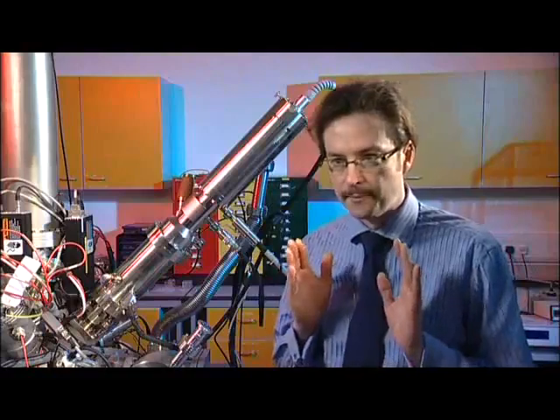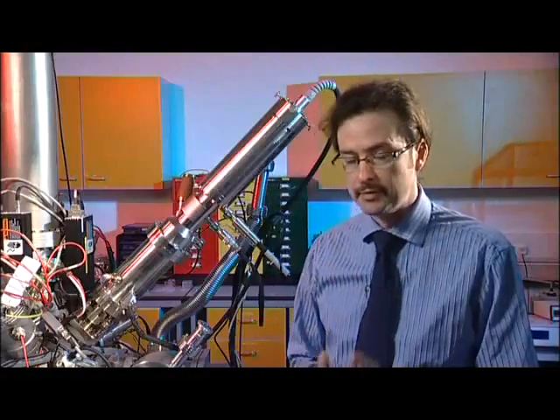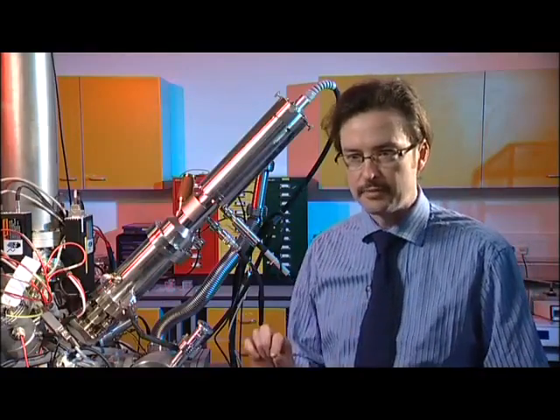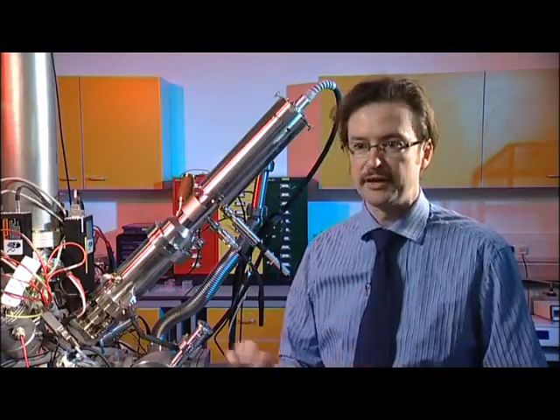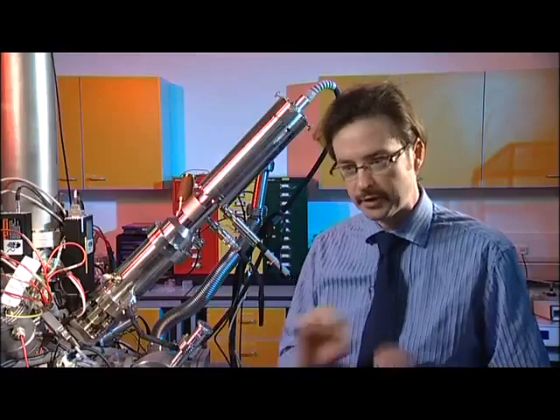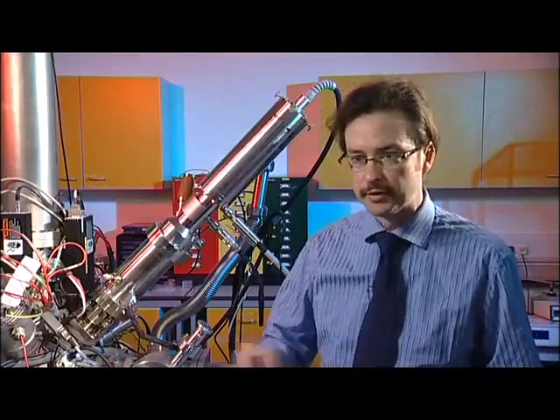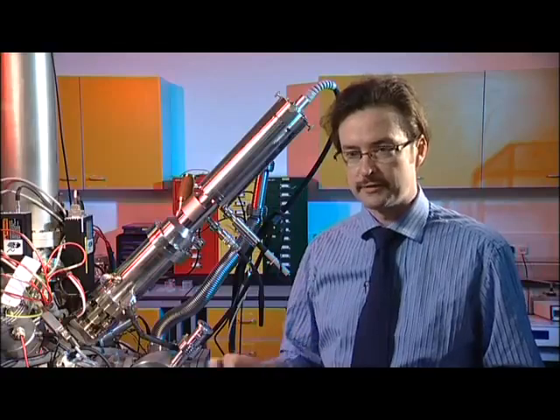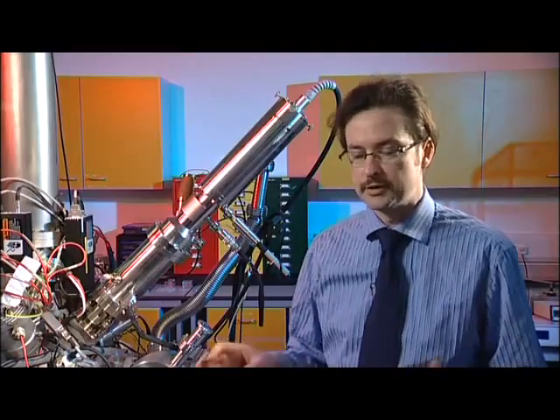And theoretically, we think we can get down to about 7 nanometers resolution. The beauty of this technique is we can then get Raman images of individual carbon nanotubes. We can image the nanotube, we can get the information about the functionalization of the nanotube all along its length, and we can also see if the nanotube's been filled by particles such as cobalt chloride. So this is an exquisitely powerful technique.